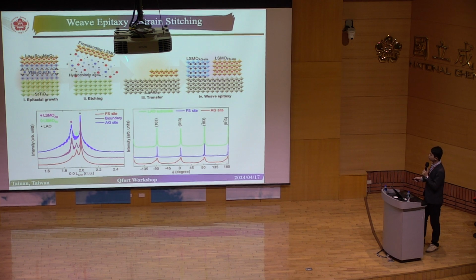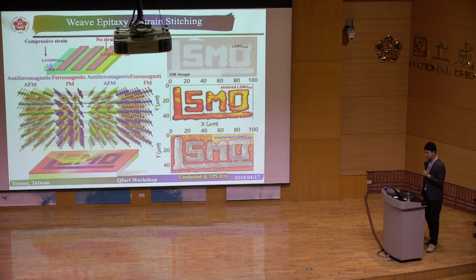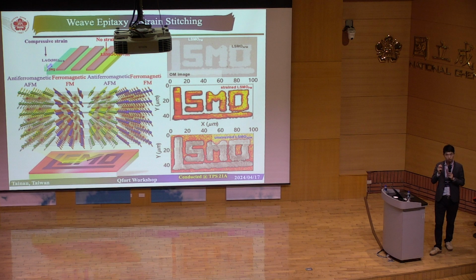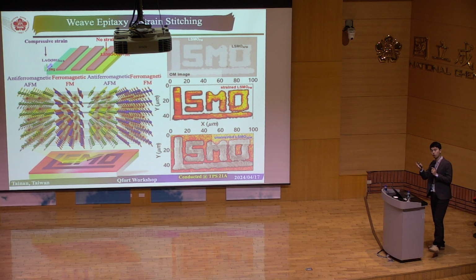So we do freestanding once again, then we selectively cover the same area, using lithography to create some pattern, and we finish the growth. Whatever you grow on the freestanding layer is unstrained, and whatever you grow on top of the substrate is highly strained. It can also be confirmed by X-ray diffraction. Now we not only create stripe patterns, we create word-like patterns.